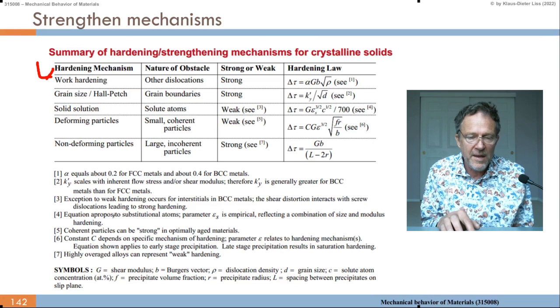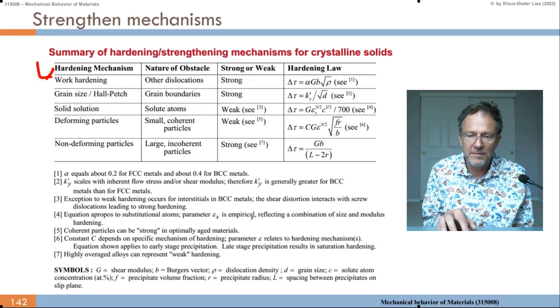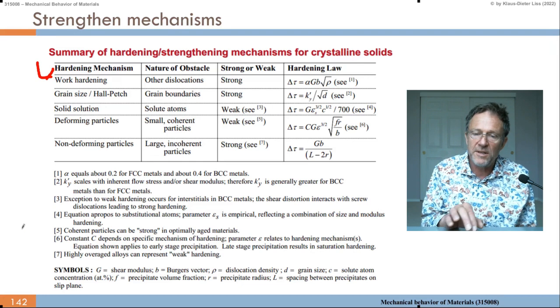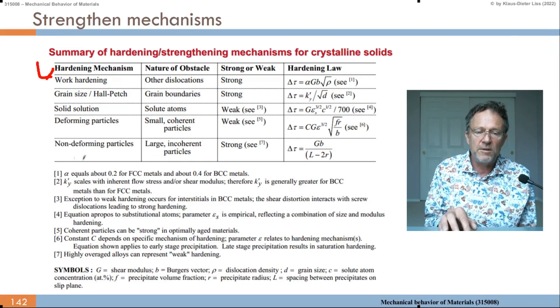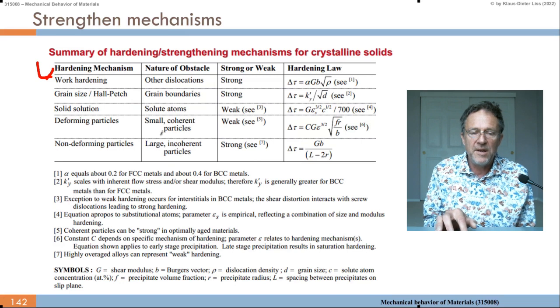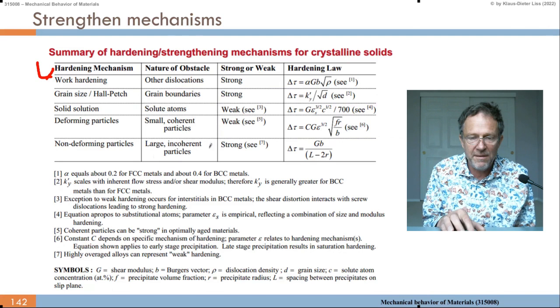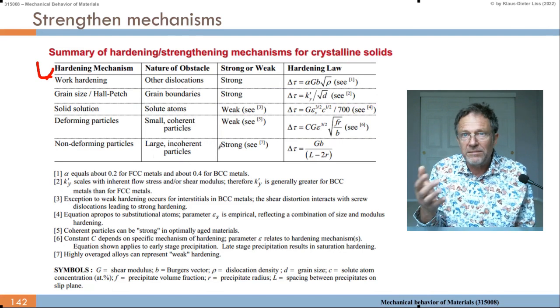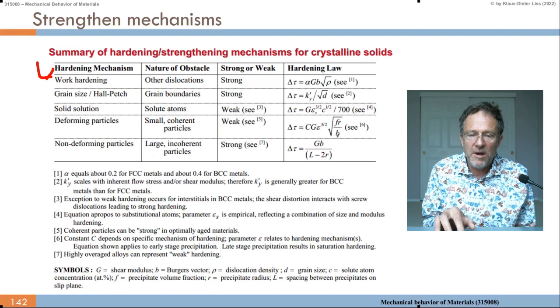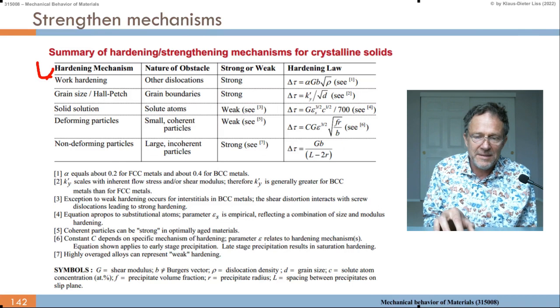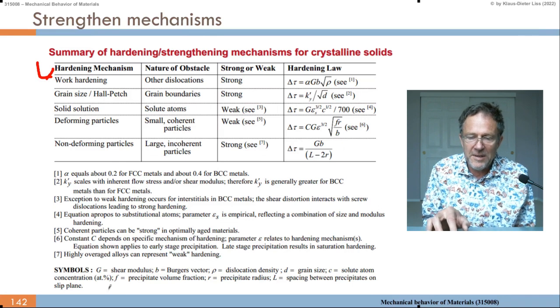The equation is apropos to substitutional atoms, and the parameter epsilon s is empirical, reflecting a combination of size and modulus hardening. So you don't go too much into that formula. And then we have the non-deforming particles. These are large incoherent particles. So you put some glass spheres or whatever into the aluminium or something similar, just an example. And that can be strong, and it depends on the spacing L between the precipitates on the slip plane and the radius.